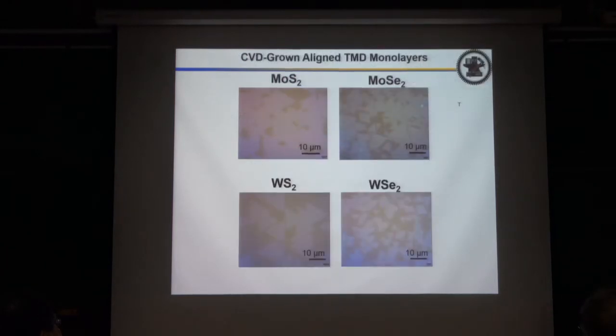So now we can grow 4 kinds of material. All of them are highly aligned. So you can see they are aligned in the same or the opposite direction. So MoS2, WS2, MoSe2, and WSe2. And then we can control the defect density.